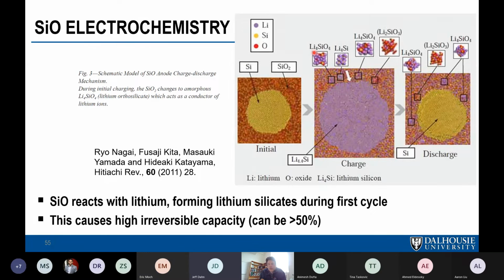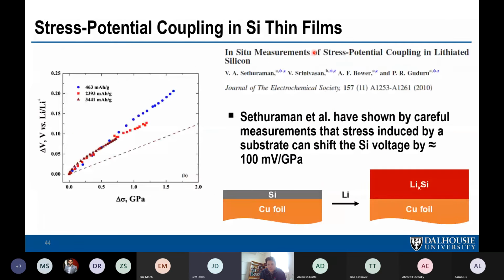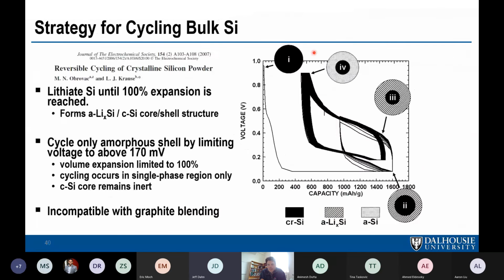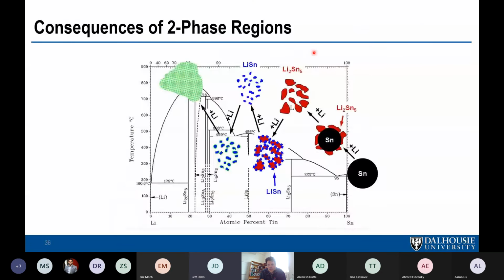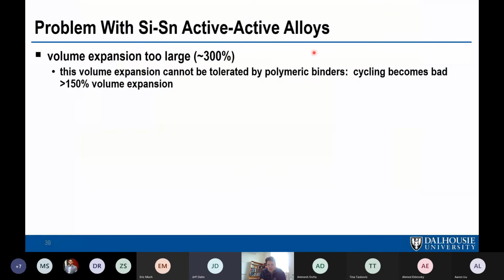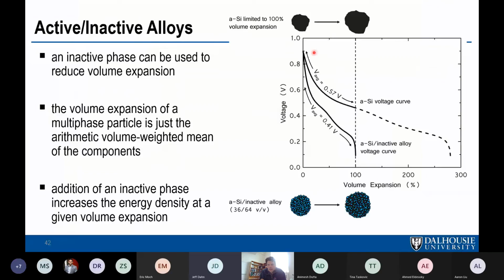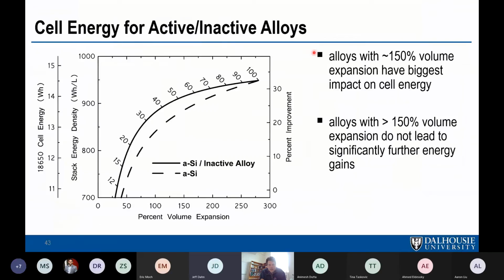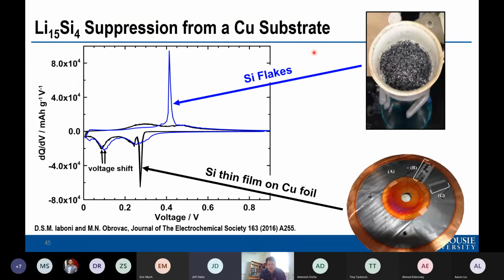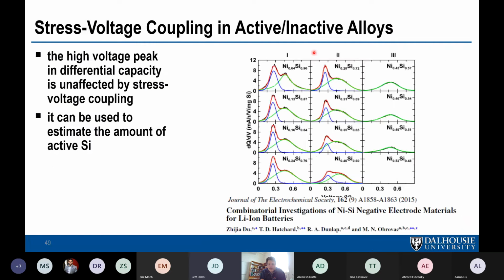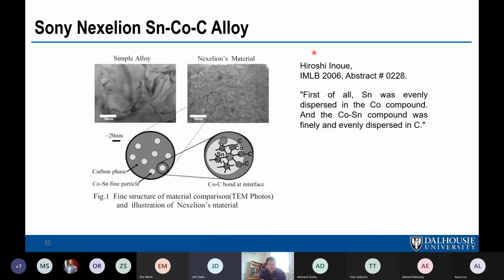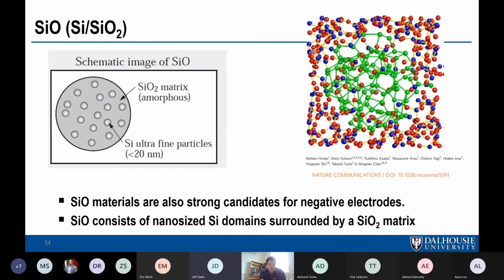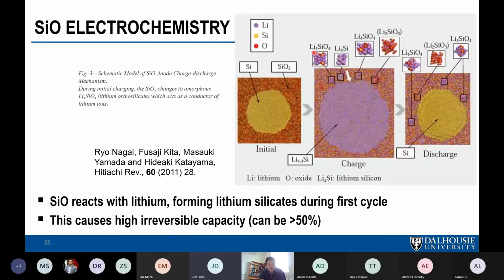Let me go back here because I think it's interesting too. I thought I had a graph of percent volume expansion versus how much alloy you have in there. But anyways, with an alloy, the percent volume expansion obviously goes down if you add the inactive phase, and as you add oxygen, the volume expansion doesn't do anything for this one. It just stays at 280%.